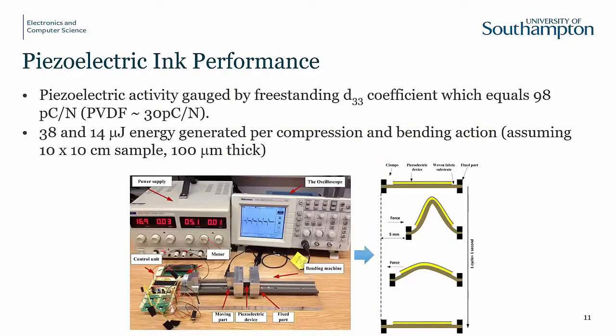But in summary, we achieved a level of activity. So piezoelectric materials are often characterized by their D33 coefficient of nearly 100. So we've got 98 picocoulombs per Newton compared to PVDF, which is around 30. So we made a big improvement on the level of activity. Plus, this is really nice to work with. And then, of course, we want to know how good is it as an energy harvesting material. So we built some rigs to sort of cyclically bend and compress materials, etc. And what we find is that despite the activity of the piezoelectric material, the amount of energy actually captured is quite low. So it's in the order of tens of microjoules per bending action or compression action.